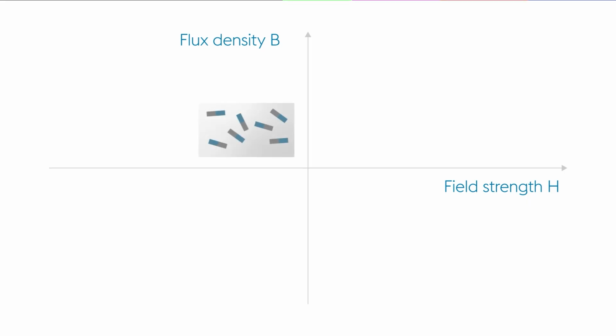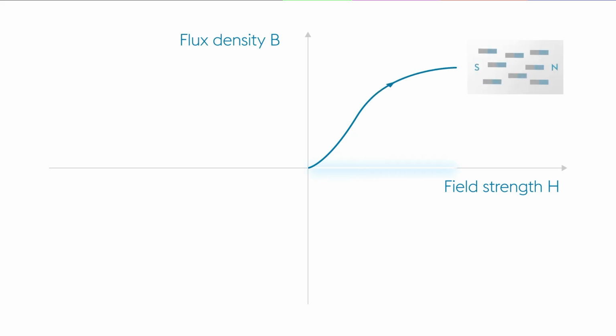I can control this by the strength and direction of the current. Flux density is found on the vertical axis, which is the number of magnetic field lines in the coil. Without current flow, the dipoles have no alignment in the electrical steel, and I have no magnetic effect toward the outside. The dipoles gradually align when the current is switched on, and the point at which all the dipoles are aligned is called magnetic saturation. This is the highest possible field gain.